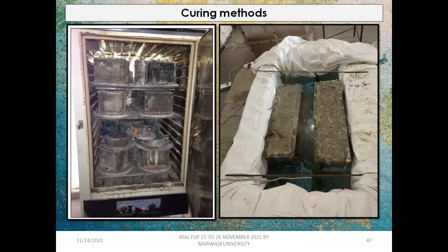These are the methods. Those who are very well known to concrete must have seen this kind of curing earlier, or may have worked with it, where you need to give external heat. But now we have started producing geopolymer without giving any additional heat for the curing requirement and polymerization. So we have started using GGBFS and silica fumes in the alkali-activated concrete, which requires neither steam nor thermal curing itself. At room temperature, you can develop this concrete undoubtedly, right? And with, I would say, better strength properties and durability properties.